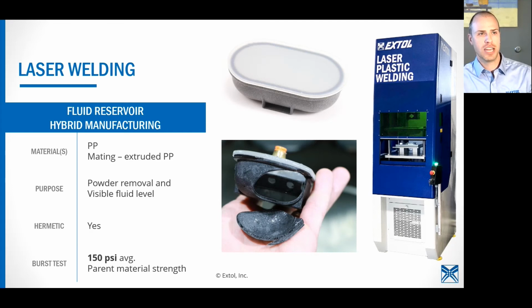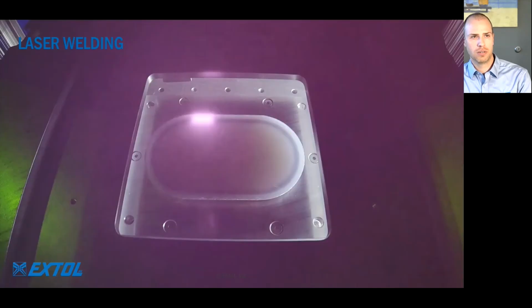So in this case, the translucent polypropylene was important because we wanted a visible fluid level, and MJF results in opaque color, so we could not see through it. But by adding this window with the translucent extruded polypropylene, we could get that performance. And again, it needed to be a hermetic seal and achieve a certain burst test.